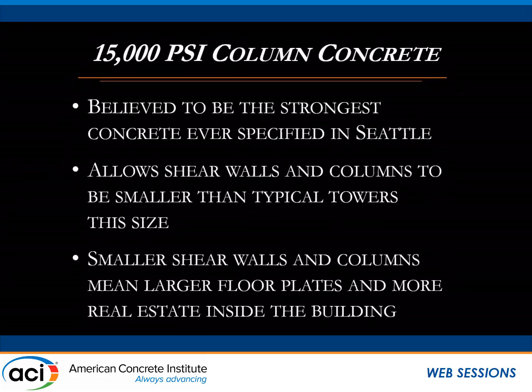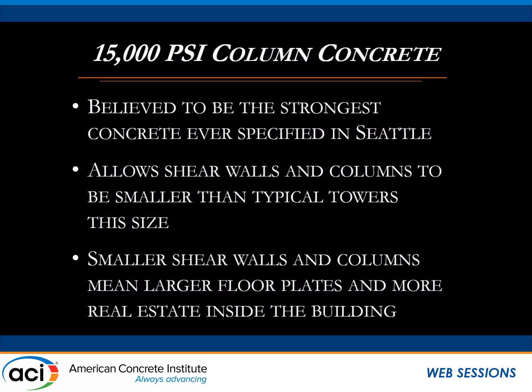I happen to hear just the tail end of the previous speaker, but he alluded to the fact that an ultra-high modulus will push your strength up substantially. There has been some higher strength concrete produced for that reason. We actually had a project a few years ago where we spec'd 15,000 PSI column concrete, and we were getting breaks up over 20,000 PSI pretty routinely. We had them as high as, I think, 21,000 on a 31-story tower.